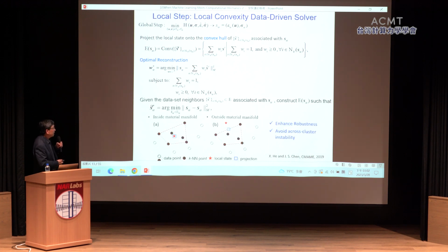Okay, so this is what is going to give it to you. If you have some neighboring data that you identify, and then you form a local convex hull, then for any projection of a physical state to the convex hull, if the physical state is within the convex hull, then it will be just right there. If not, then what it gives you is the closest point projection onto the local convex hull.